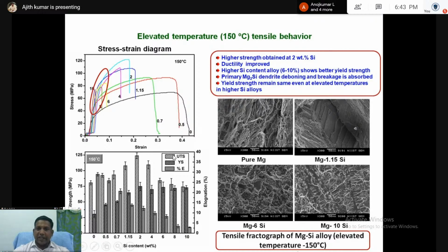The yield strength remains the same even at the elevated temperature in high silicon alloys. So we can correlate this tensile property with the fracture analysis. So fracture studies: what is the reason for the tensile changes that we can identify using these SEM images?